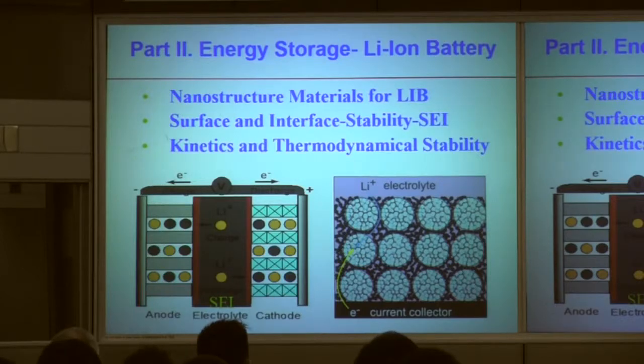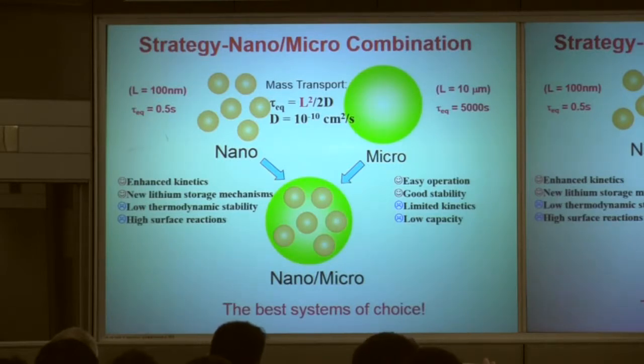Second, we prepared a lot of nanostructured materials for lithium-ion battery. For the lithium-ion battery, we try to make some materials we call the nano and micro composite materials. Because in the lithium-ion battery system, we need a very high electron transfer, and we also need the stability of the nanoparticle. If you make a very small nanoparticle, the electron transfer speed will be very high. But the stability of a very small nanoparticle is not so good. That means this nanoparticle, because the surface area is very big, is